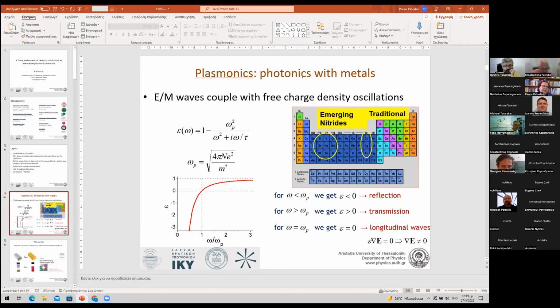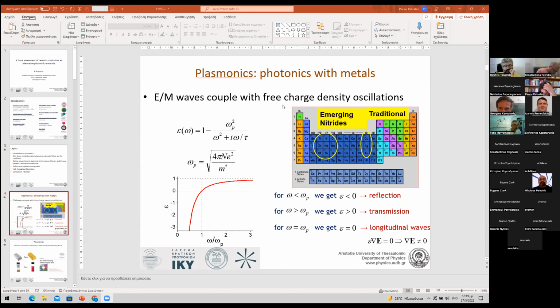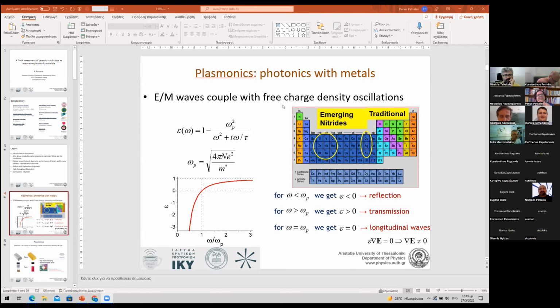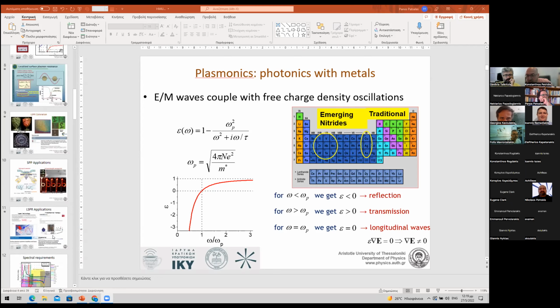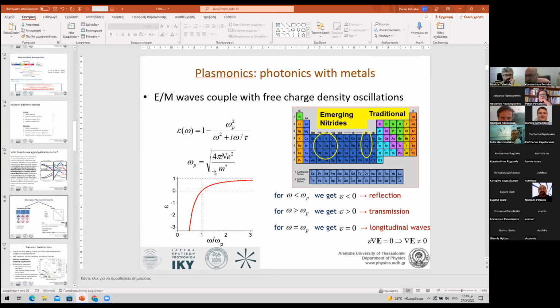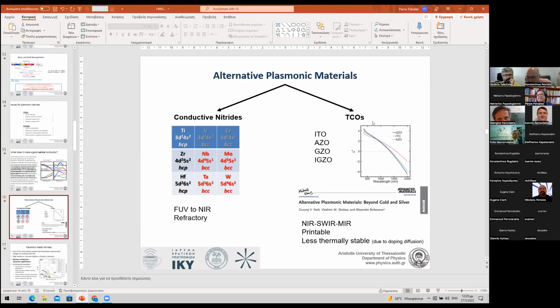Regarding the silicides, I'm not very familiar. I have the impression that the silicides have less carrier density than these nitrides, so they would be more comparable to the TCOs. That means that they would have some resonance in the mid-IR and so on. Comparing the TCOs with silicides, I have not done that, so I cannot tell you if they're inferior or superior to TCOs, but I would say that the silicides are, from the optical point of view, closer to the TCOs than to nitrides.